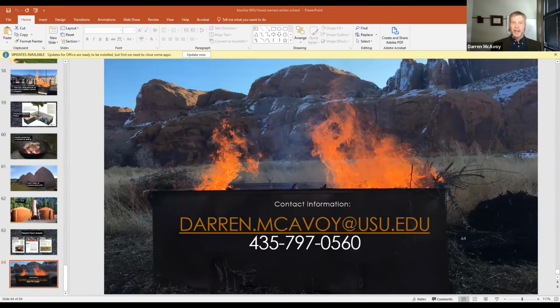Yeah, thanks for asking. Temperature, essentially. Gasification happens at 800 degrees Celsius, pyrolysis at 400 to 600 degrees Celsius. With gasification, all the material turns into a gas, like propane, and a tiny bit of it turns into biochar. With pyrolysis, especially in high-tech machines, we can separate out the bio oil through thermochemical decomposition. At the time in 2014, we were more about the bio oil than the biochar, but it also produces syngas. I think that answers your question.